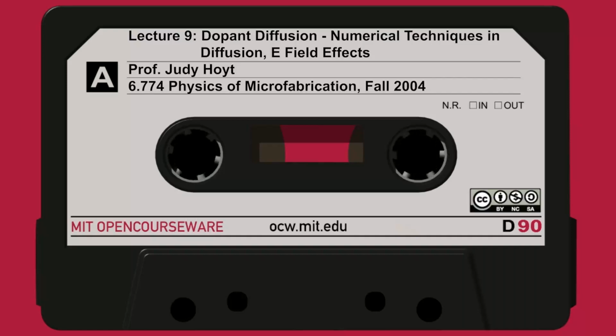Okay, let's go on to slide number 13. Now that was the case we just talked about, assuming we had implanted the dose. Let's just take the case where we used a gas phase pre-deposition step as an example to get the boron initially into the wafer, and say that was done at 950. You can then use the charts in your book or in the handouts to look up the solubility of boron at 950, and you'll see it's pretty high. It's 2.5 10 to the 20.